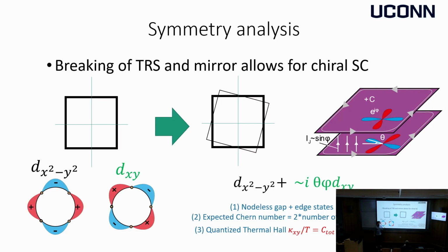This seems too robust to believe, unless there is a symmetry argument. And of course there is. If you start with the square lattice, where the d-wave order parameter is well defined by symmetry, there's actually another d-wave order parameter that's obtained by rotating this one by 45 degrees. And they are distinct in symmetry. Specifically, the mirror planes that I've drawn here change the sign of this order parameter, but not this.